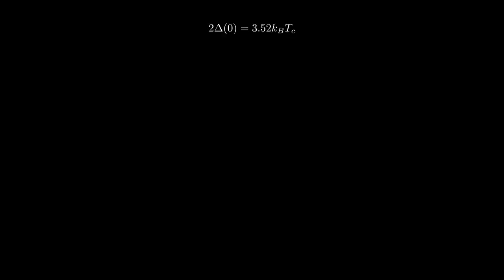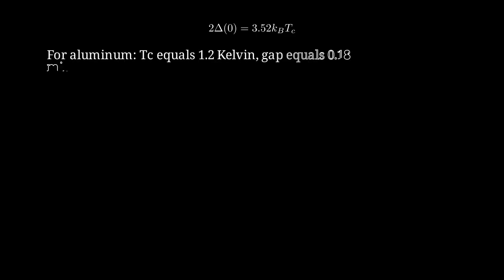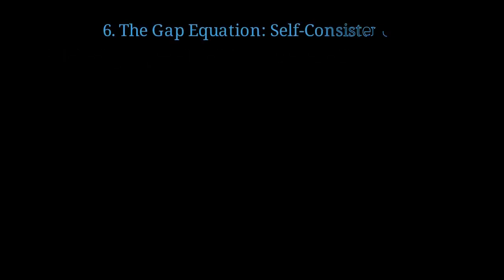The zero temperature gap is related to the critical temperature by this universal ratio, 2 delta_0 equals 3.52 times kB Tc. For aluminum with a critical temperature of 1.2 Kelvin, the predicted gap is about 0.18 millielectron volts, in excellent agreement with experiment. The gap delta satisfies a remarkable self-consistent equation.